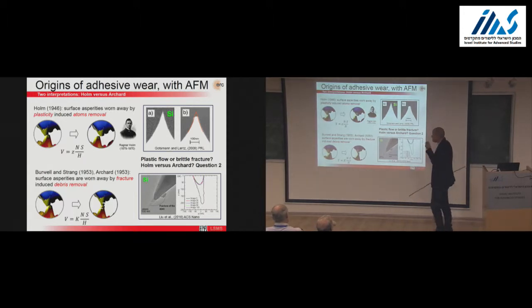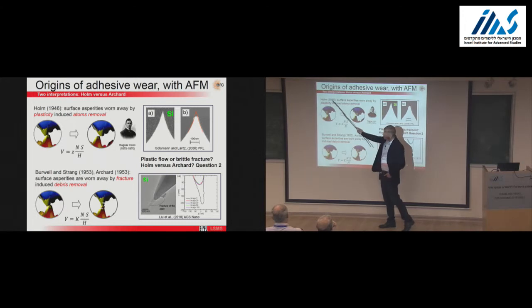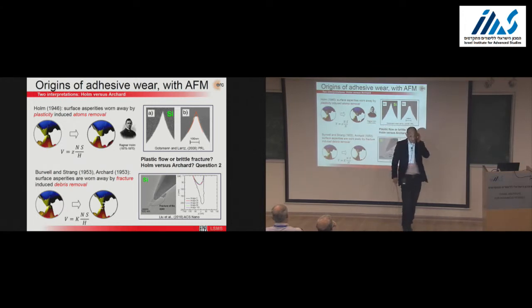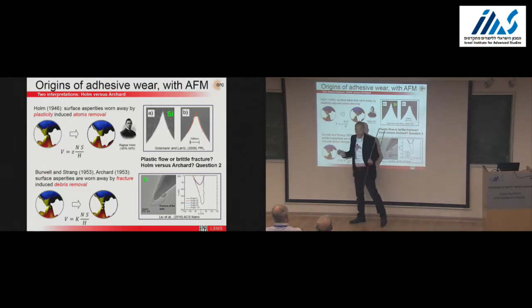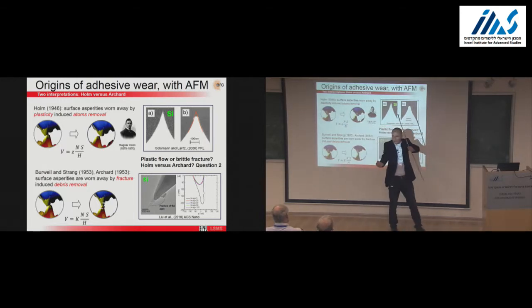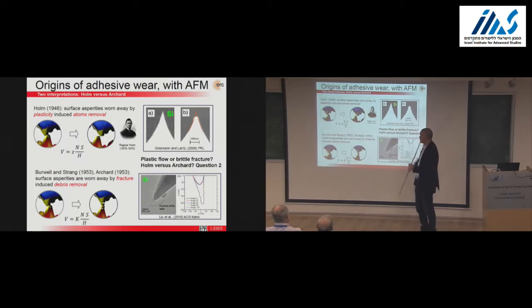And in fact, the contribution of Holm that preceded Archard in the 1940s got revived in the recent literature, where it was argued from Holm that when you form an adhesive junction, you will transform the mechanical work into plasticity, into plastic shearing, and a smooth transformation of a roughness.